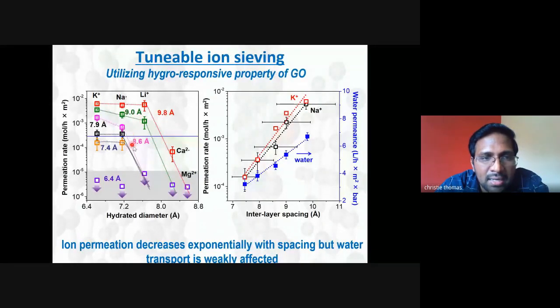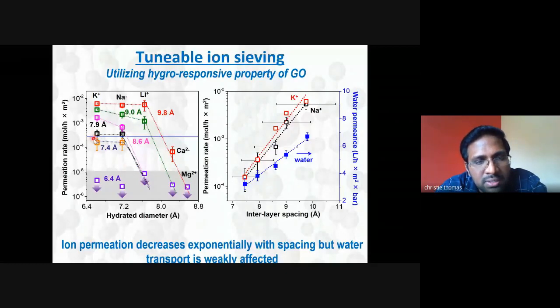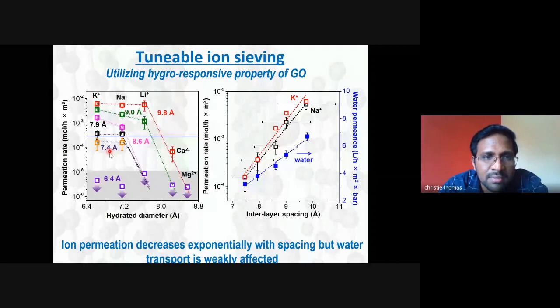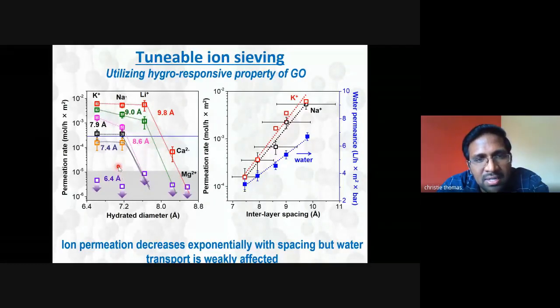So different graphene oxide membranes with capillary sizes of 9.8, 9, 8.6 angstrom and so on have been made, and you can see that as the capillary size goes down, the salts get rejected. For the largest capillary, 9.8 angstrom, you can see that Mg2+ is getting rejected. But if you look at the purple one, the 6.4 angstrom capillary GO membrane, you can see all the salts are getting rejected.